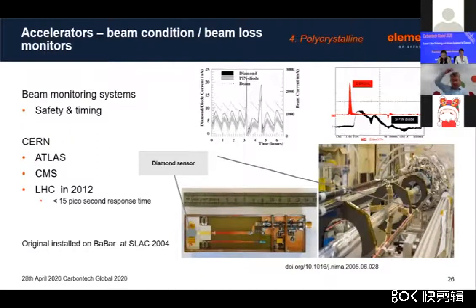And the applications of those came soon after. And the reason, as I show you here, is they're used in the beam safety monitoring in particle accelerators. And if I show you here, here's the response. The black line is a response from a silicon diode, and here's the response from a diamond diode. And it's this very fast response time, coupled with its radiation hardness, that enables people to embed the detector within the beamline. This is an accelerator called BaBaR that's at the Stanford Linear Accelerator Laboratory in California.